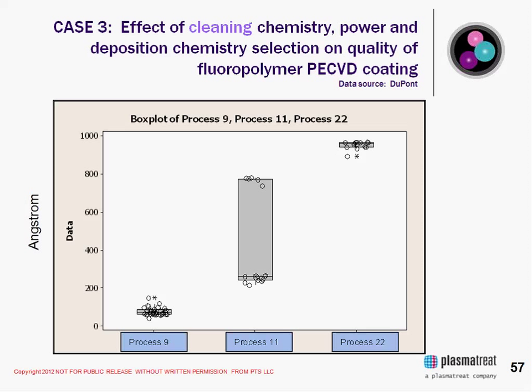Yes, so there's a couple of things. One is some technologies that are practicing wet coating, dip coating, for example, that may be used as an antimicrobial. Parts may be fixtured and treated in a plasma system to activate the surface, and then the rack is pulled out and we go into a subsequent step. Within our chamber, we can run a multiple step process. There was a slide where I showed the five different types of processes that we typically practice. We can activate a surface and then put down something on top of that surface. As far as selective, you do need to look into masking if you wanted one area to be treated and not another. And customers have evaluated a variety of different masking techniques. Did that answer your question? Yes. Okay.